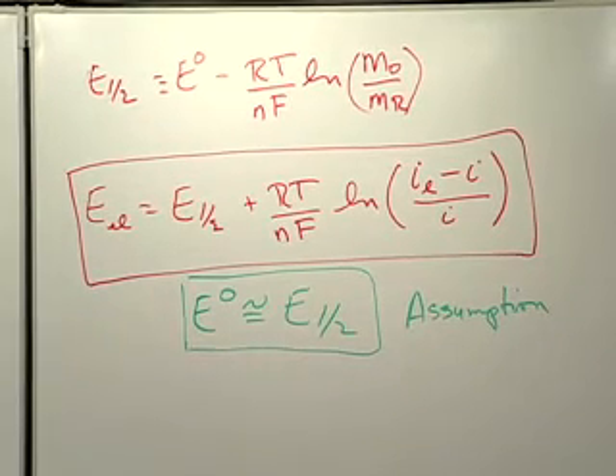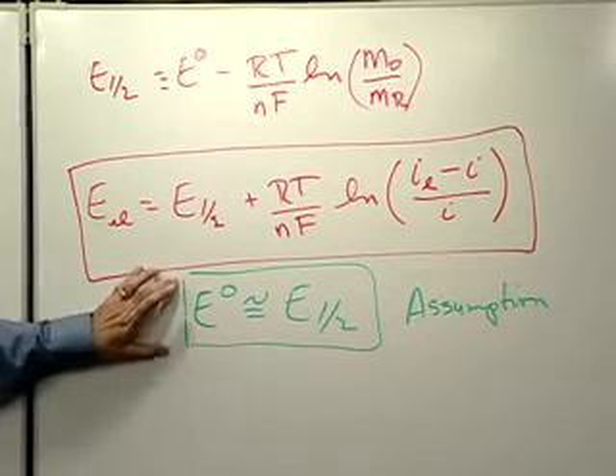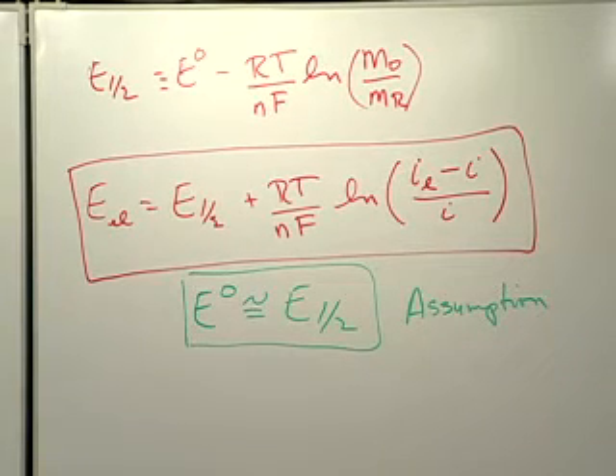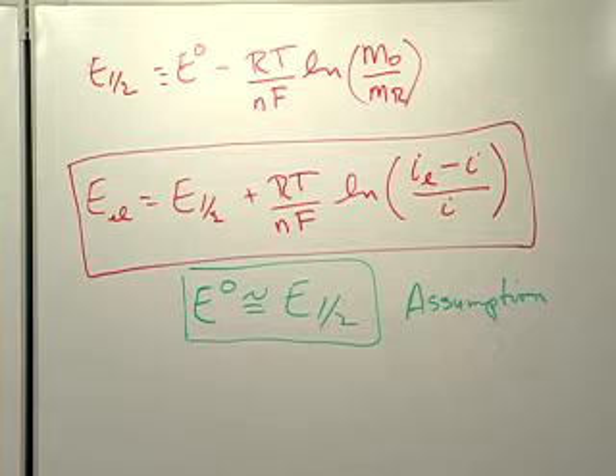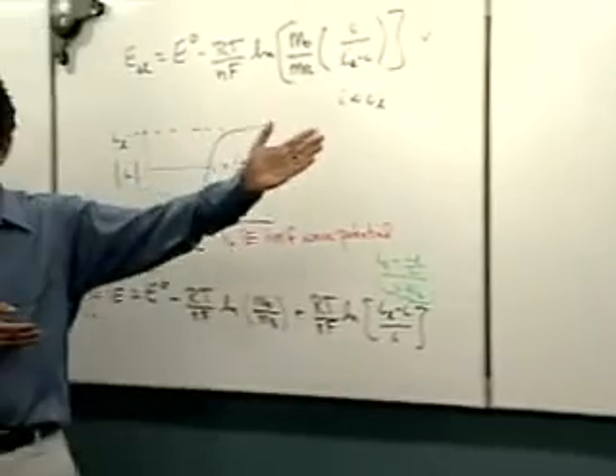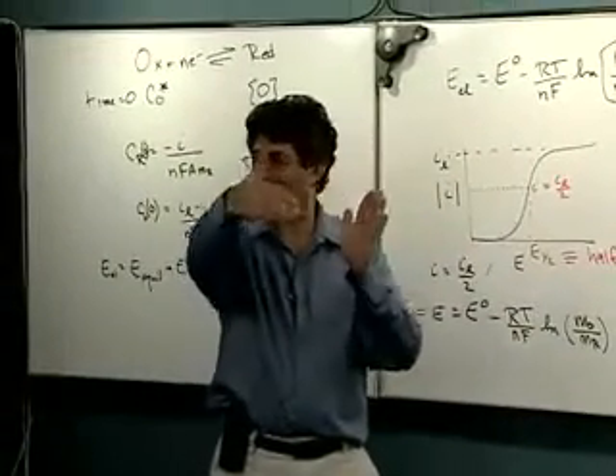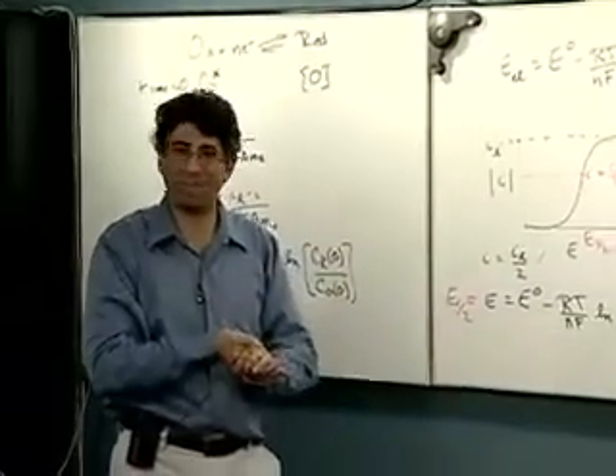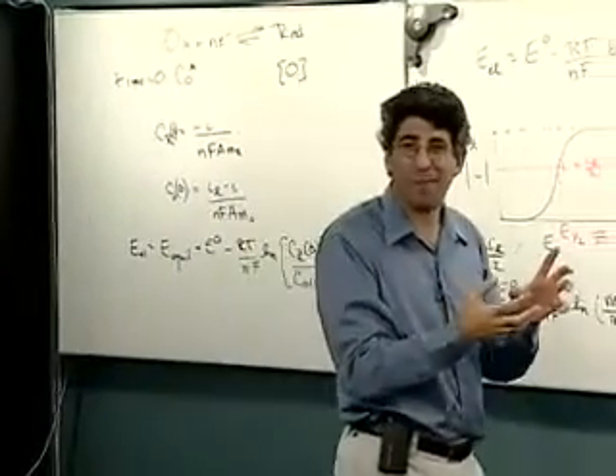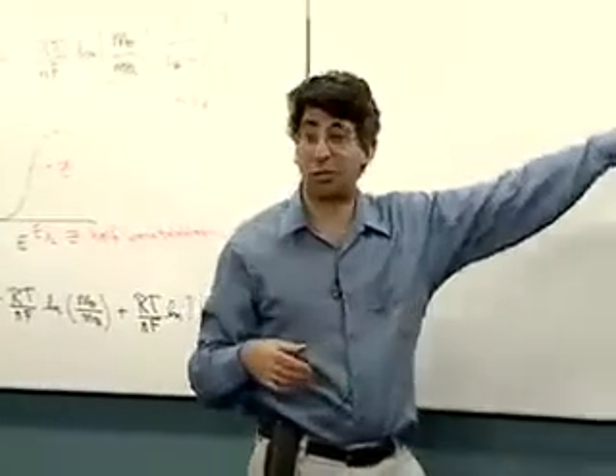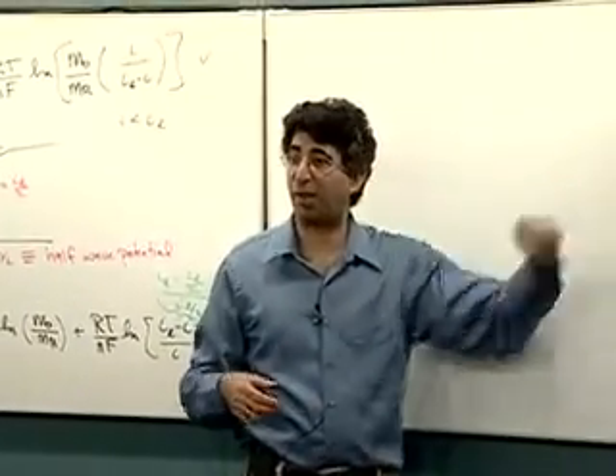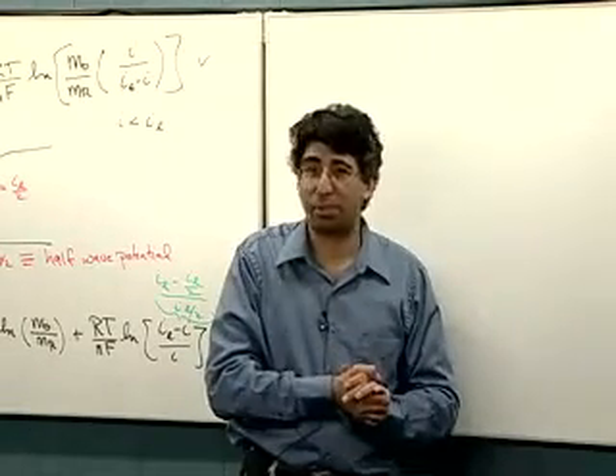So there is a pragmatic reason for doing this, and that is until that diffusion coefficient really changes, order of magnitude change, you're not going to pick up the fact that E1/2 is different from the standard redox potential. And so if you were assigned the job of making up the table of standard redox potentials, you wouldn't want to do it this way. Right, because it doesn't have enough accuracy to get 10 significant figures for the standard table that everybody's going to memorize. And you want to do it actually by some sort of a direct titration technique where you can get a lot of accuracy and precision in the measurement and the reported number.